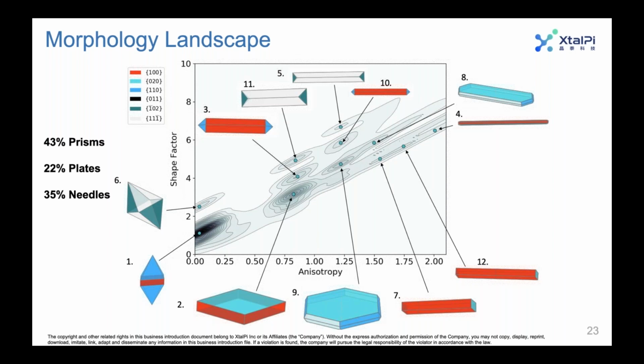So by varying the surface area, you're effectively, if you increase the surface area, you're essentially saying, what if that face grew more slowly? And we do that for all of the faces, and that's how we get all these different shapes. And then we calculate the variables, the shape factor and the anisotropy. So since we're manually changing those and calculating these descriptors, I don't know that there's an error bar associated with that. But then the contours themselves come from a kernel density estimator based on these two descriptors. So I hope that answers your question. Maybe I can discuss with the team and get back to you if there's any particular errors we think would be for this. But I think because it's manual, there wouldn't be any specific errors there.